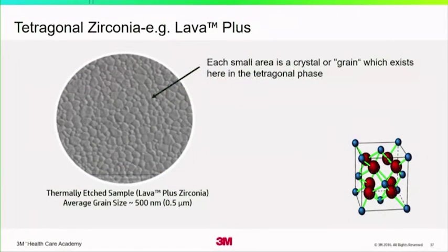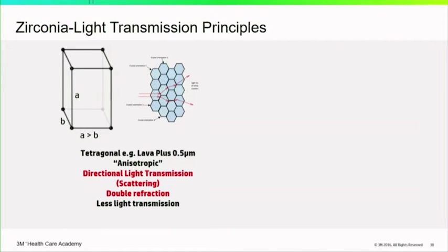If you look at Lava Plus, which is a tetragonal zirconia, you can actually see the crystals. This is an example of a thermally etched sample of zirconia. The particle size for this material is right around the average of 0.5 microns. And this is how the material exists in its tetragonal phase. If you think about light transmission and why zirconia may appear to be dead, with tetragonal zirconia the shape of the crystal itself redirects light in such a way that it creates a number of boundaries where each particular grain, as light passes through it, redirects the light in a different direction. This effect, known as refraction, or in the case of tetragonal zirconia, double refraction, scatters light. And it scatters light to the point where the restoration itself can look dead or relatively opaque.